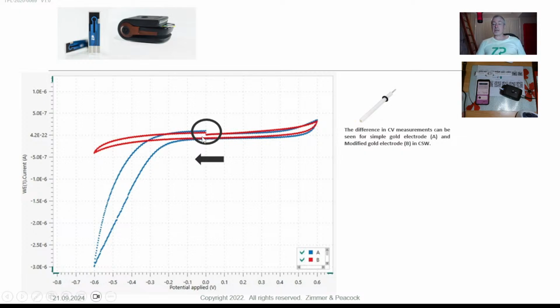The reason you don't see it in papers too often is because they don't show you the first scan, they show you the second scan. By the time you get to the second scan, you will have lost that discontinuity in the data. It's because you started the experiment in a place where there was a little bit of electrochemical activity. If you just reported on the second scan, you wouldn't have seen it. It's not talked about too much, and it's not in textbooks, because it's one of those experimental details that people know about. It's not even taught, but once you start doing cyclic voltammetry, you become aware of this. It's not an issue, it's just a feature of where you started the experiment.